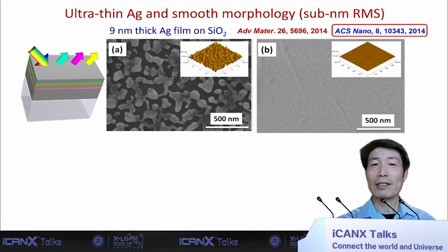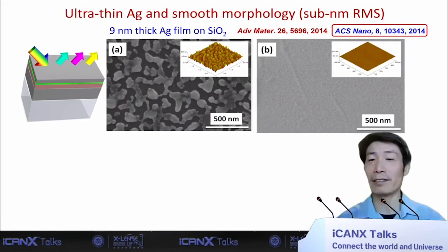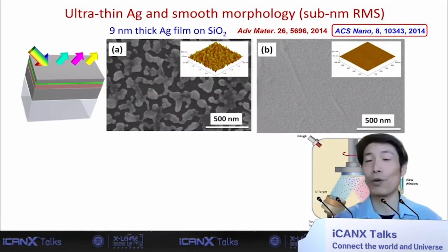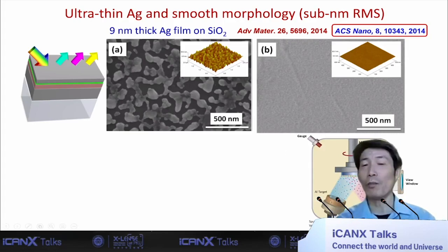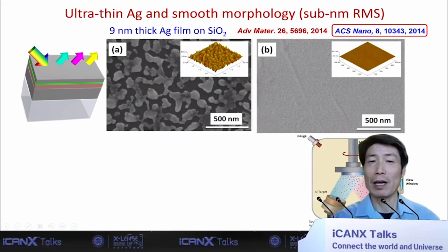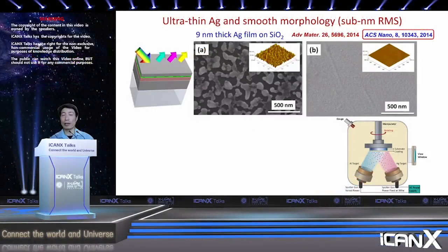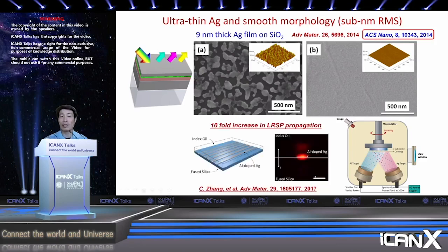And this is done not by using pure silver, but by adding some other impurity, if you wish, doping, a small amount. In this case, for example, adding a small amount of aluminum, you can actually make it smooth. Making smooth silver is actually a pretty big deal, because silver is perhaps still the most widely used material for plasmonics, a very important field of nanophotonics, metamaterials, and so on. We show that if you make the silver smooth, the surface plasmon mode can propagate 10 times longer by reducing the roughness.